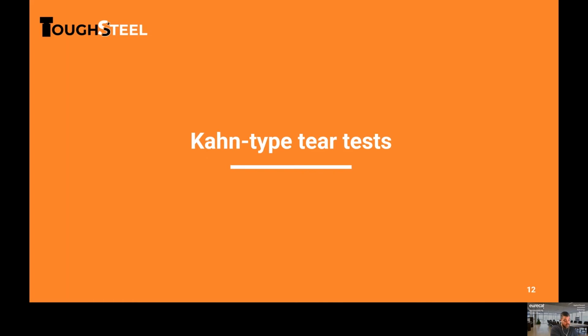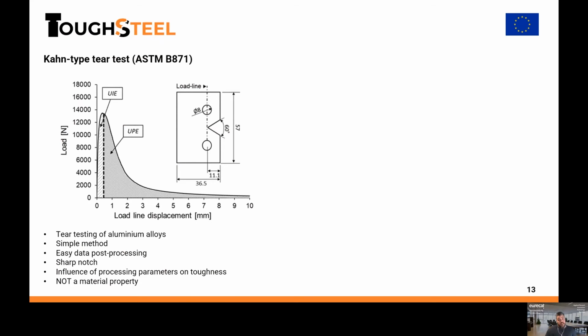Finally, let's talk a little bit about another interesting method that has gained increasing interest over the last years. It has also been used especially to characterize the tear testing of aluminum alloys. This is the Kahn-type tear test. Actually, this test was developed to evaluate the notch resistance of aluminum alloys. And the procedure is described in the ASTM B871, although this standard was withdrawn in 2017. But of course, it could still be applied to evaluate the notch resistance, the relative toughness, let's say, of the material.